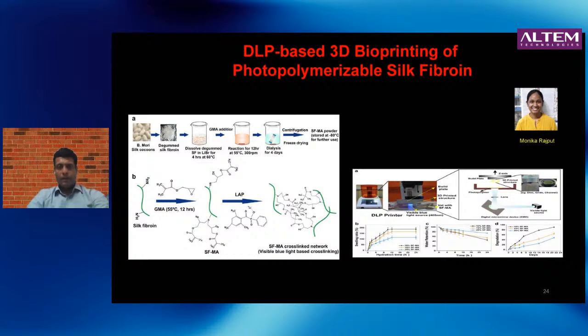So you start with the silk cocoons, you do this degumming, then you dissolve it in lithium bromide solution, you dialyze it, and you lyophilize it to collect the powder. And then what we do is react it with glycidyl methacrylate so that you can introduce an acrylate group on the silk. What that does is it becomes photosensitive.